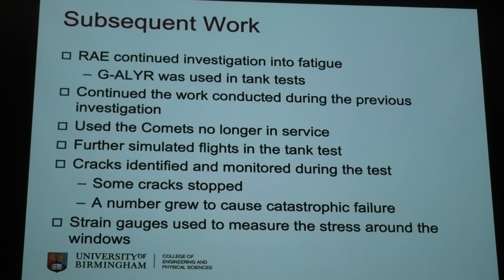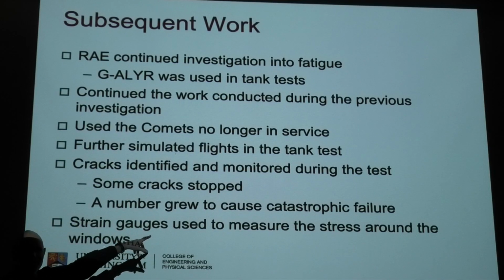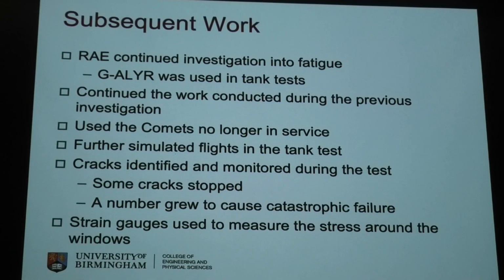Further simulated flights in the tank test were done, and then they turned over the tank test to other airframes. What happens to other aircraft? Can we check out, before an aircraft goes into service, can we take it down to the RAE, stick it in the tank and make sure that it doesn't fail at 3,000 cycles? And that's what the tank got developed for. Cracks were monitored during the test. Some cracks were stopped, some grew, and they were allowed to grow out to catastrophic failure. So there's lots of bits and pieces of data as they just gathered data. And they were trying to learn more and more about airframe fatigue.